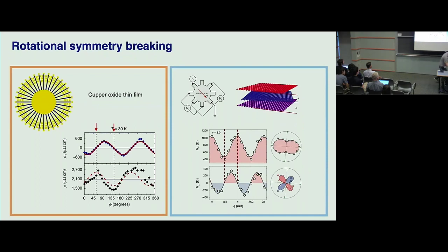In the data that I didn't show, these are two configurations. We fit them independently. And if you use a single conductivity matrix and fit them, you realize they are off by about 10%. So the 10% difference, if I plot them together and fit a single line, it's almost hard to tell, right? So I cheated, and you called me on it.